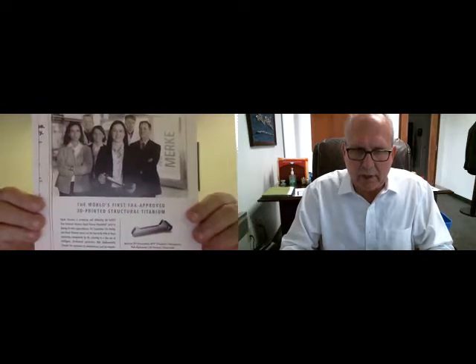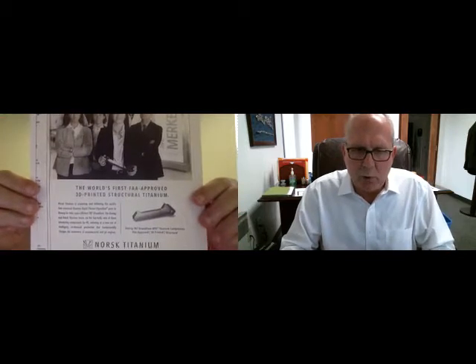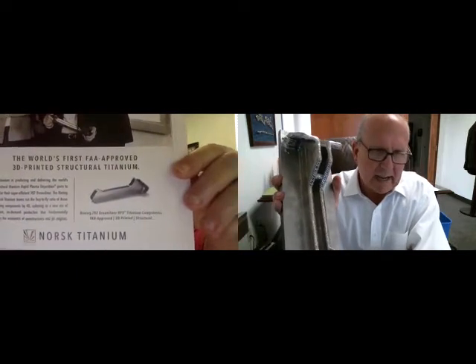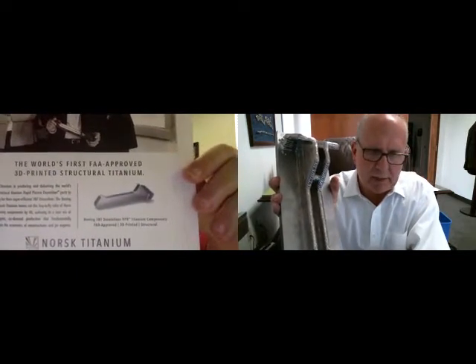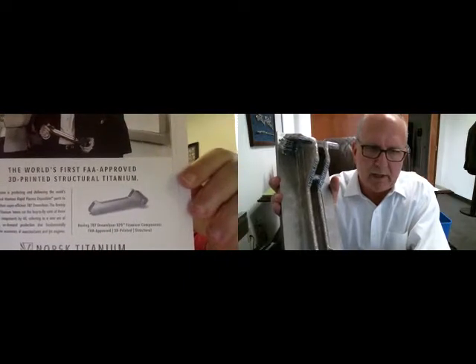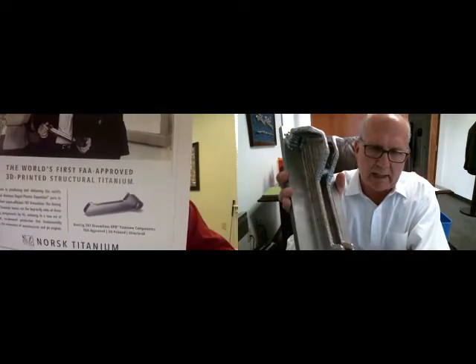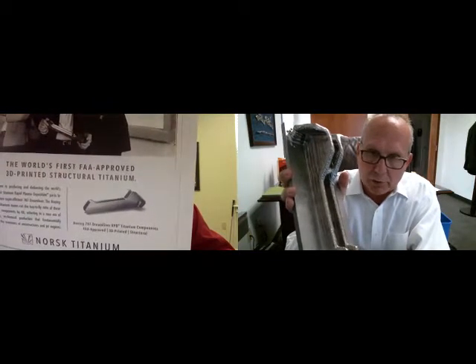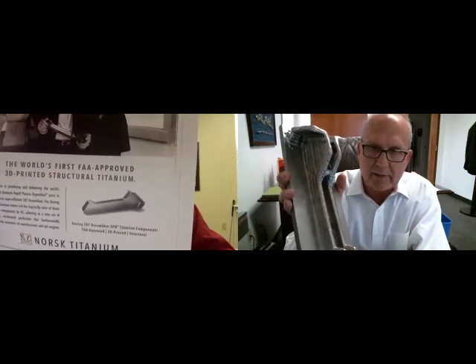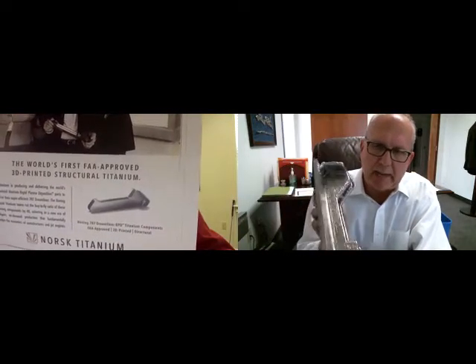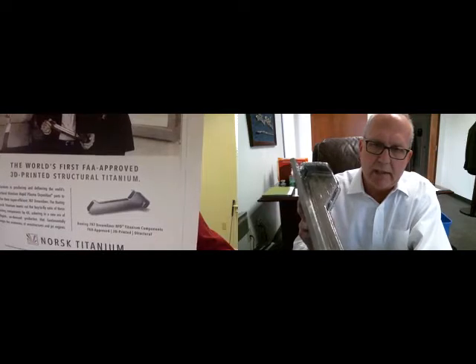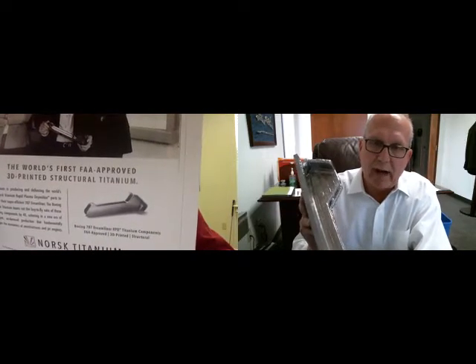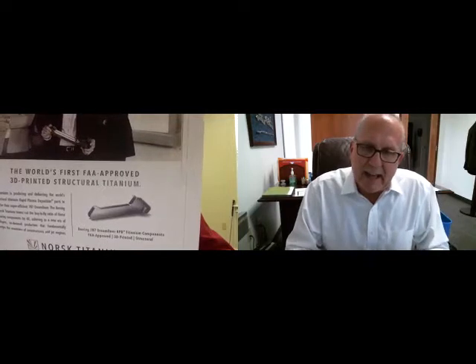This ad is for the customer. The customer is Norsk Titanium. And if you see in that bottom corner, that's the finished product of this part. As you can see, this is going in the 787 Dreamliner, and it's an FAA approved 3D printed structural component. That's the first one that I know that's structural that will be flying in the aircraft. And we were very instrumental in getting this part to full density and to get it qualified for flying in the aircraft. That's called the electron beam arc method.